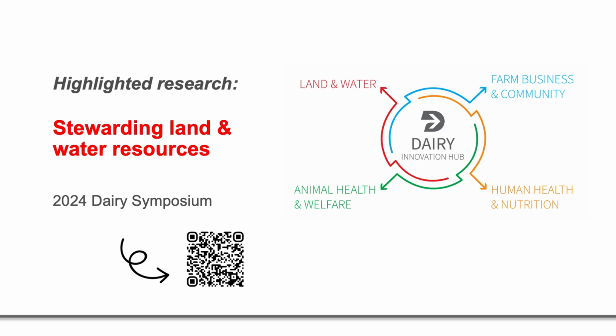Yeah, so in our study right now, we actually didn't see a reduction in methane. There may be some small reductions, but if you look at the significance, they're not statistically different, really. We haven't seen any huge reductions in methane. In terms of the ammonia side of things, it's a little bit of both. That floating cover is trapping the ammonia in. Biochar also has a very high affinity for ammonium and ammonia absorption. And so we did see an increase in the ammonia concentration on the biochar after the study, where it did soak up some of that ammonia that could have potentially been lost. So it's a little bit of both.